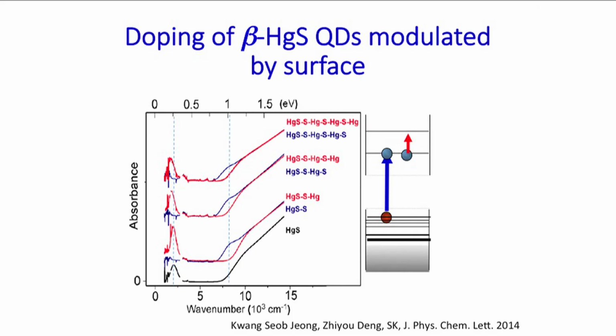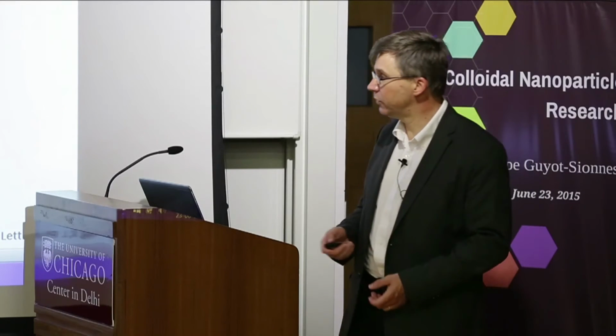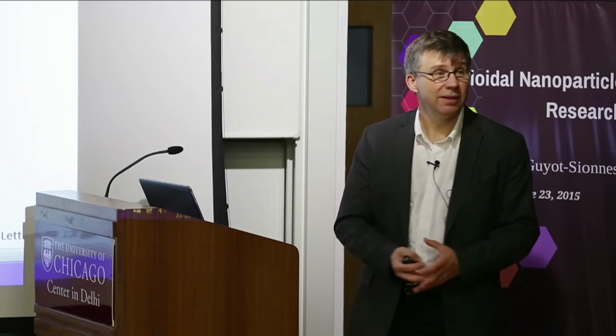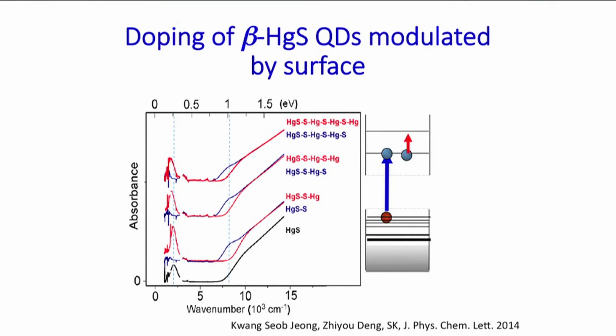So if we take the mercury sulfide and take the spectrum of it as it is coming out of the reaction, we have this peak here, which we assign to that intraband transition. And then all we do is add some sulfide to the solution, S2 minus. And this S2 minus is probably going to bind to the surface of the particle, but it makes the spectrum change by creating absorption in this range and removing the absorption that we had from the intraband. So somehow the intraband transition disappears when the sulfide is added to the surface. So, okay, maybe the electron transfer. But then when we put mercury on the surface by adding mercury ion, then that peak reappears, and so on and so forth.